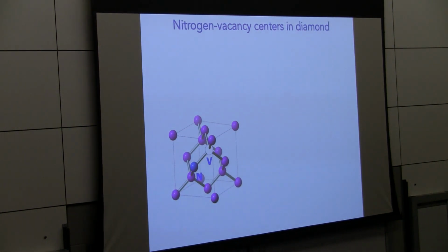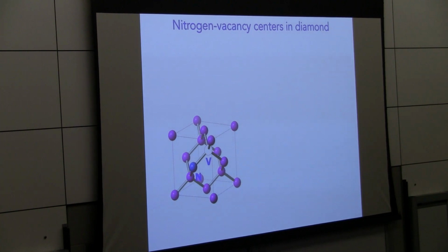So now, taking a step back to be a bit more complete in my introduction of what the NV center is, it is a defect in diamond in which a single carbon atom has been replaced by nitrogen, and nearby there's a vacancy. These can be formed a variety of ways. They occur naturally if you just dig a diamond up out of the earth. You'll probably find some of these. They can occur via implantation. One can implant nitrogen ions to generate those nitrogen substitutional defects, and in that process you also generate vacancies. One can also grow these defect centers into diamond, something that we actually do. I won't talk so much about that, but that's another way: one can use chemical vapor deposition growth to grow diamond with these defects inside.